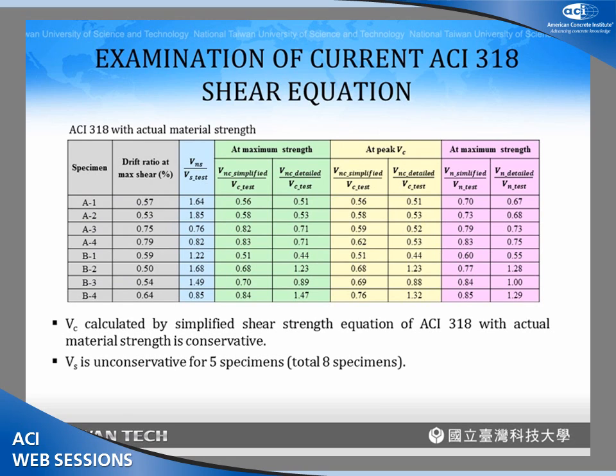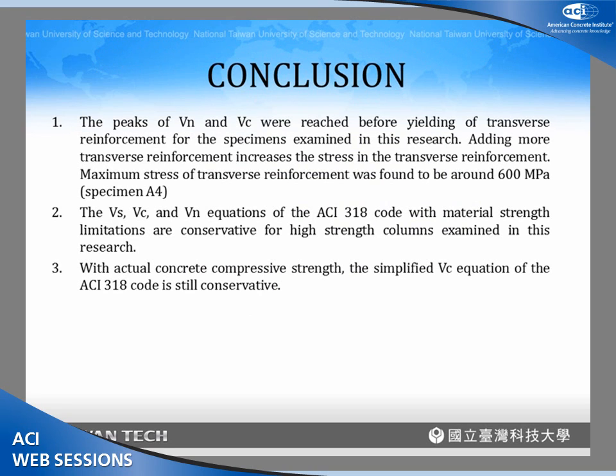And we did the comparison again, and we found that, of course, the Vs has become unconservative, right? Because I mentioned earlier that the stress in the transverse reinforcement did not yield at the peak applied shear. However, we found that the Vc from the simplified shear strength evaluation is still conservative, even with the 120 megapascal for f'c input into the shear strength equation. For the detailed shear strength equation here, I think there is still some problem. I need to talk to my students, so we don't have any conclusion about this one.